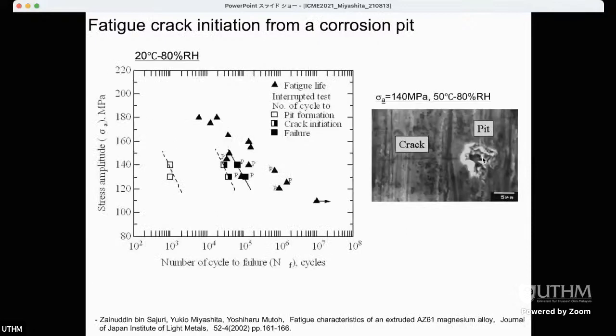And after the pit grows to some size, fatigue crack starts to initiate from the corrosion pit like this. So first the corrosion pit initiates, the size of the corrosion pit increases, and then a crack starts to initiate from this corrosion pit.